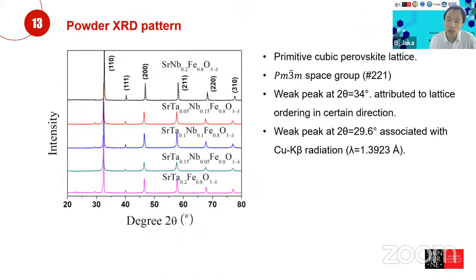Okay, so we would like to check the effect of the doping. As we replace the tantalum with the niobium, you can see that in here tantalum is 0.2. In here we replace 0.05 of tantalum with niobium. In here we replace 0.1 tantalum with niobium. In here we replace 0.15 of the tantalum with the niobium. And then we go to the other extreme where we replace all the tantalum with the niobium. We can see that all of them